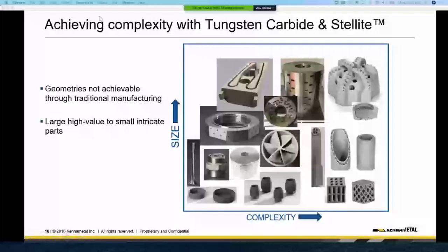And this is one of our larger stellite parts. This is a flow control stack that measures about 12 inches tall. And if you look, this is a cross section of it. While it doesn't look particularly interesting on the outside, one of the things that we are leveraging with additive a lot with wear components is the ability to do very complex internal flow channels. And you can see that with the cross section here taken from this part. And you can see the flow channels in a section of this part as well.